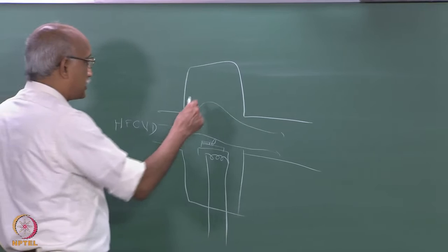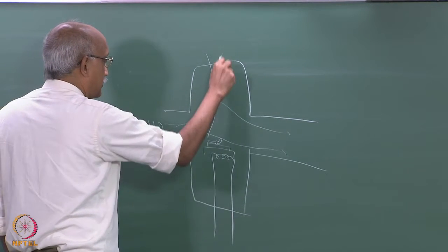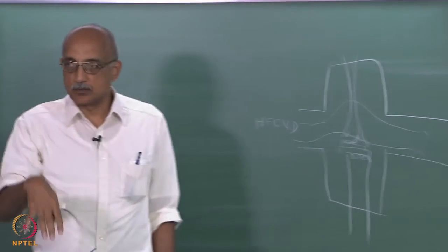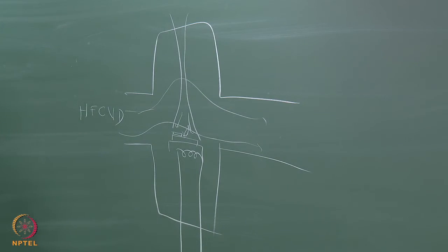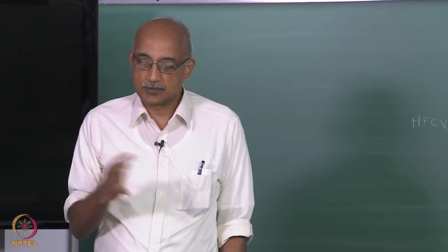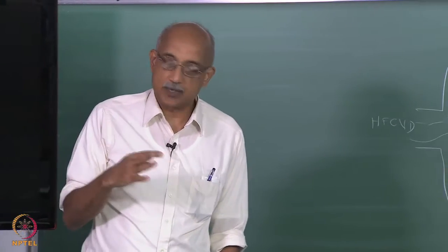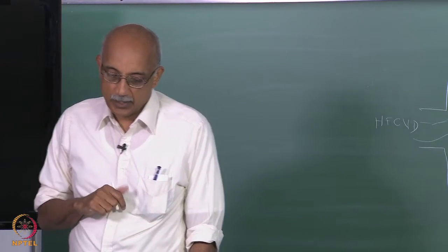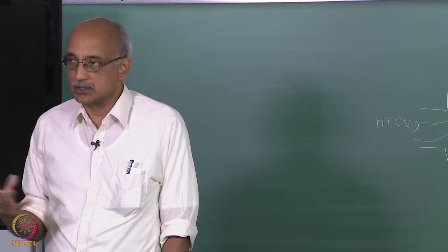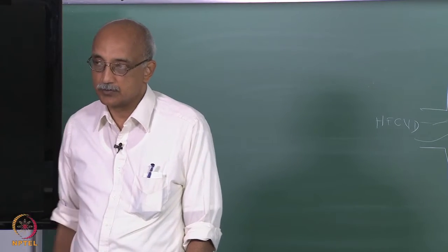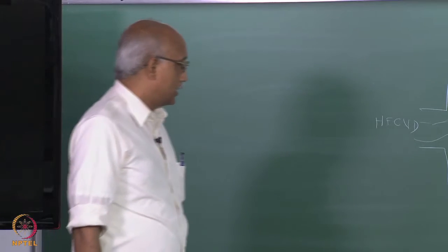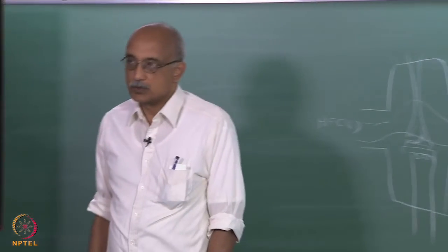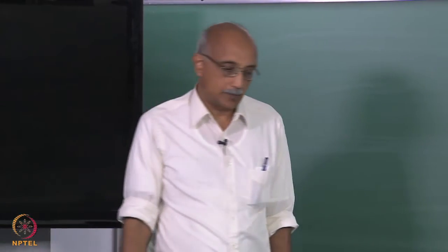Another variant on this that we discussed is a stagnation flow reactor, where the reactants enter in a vertical flow, setting up a stagnation layer around the substrate, which helps in terms of maximizing the residence time of the reactant species and therefore maximizing the deposition rate and the uniformity of the film on the surface as well. And the stagnation flow CVD systems are also used quite commonly in various applications.